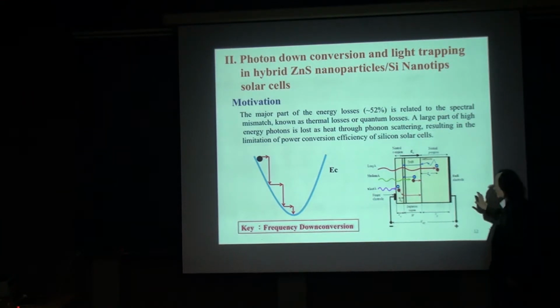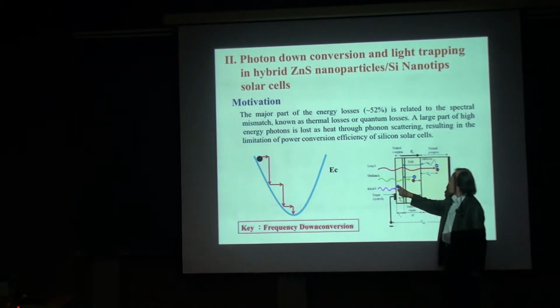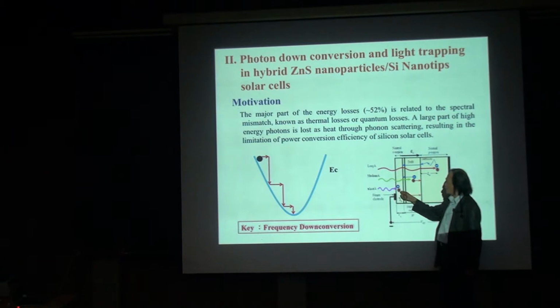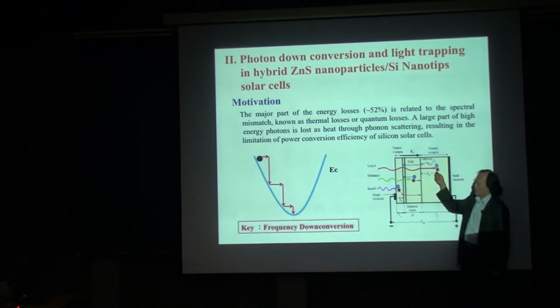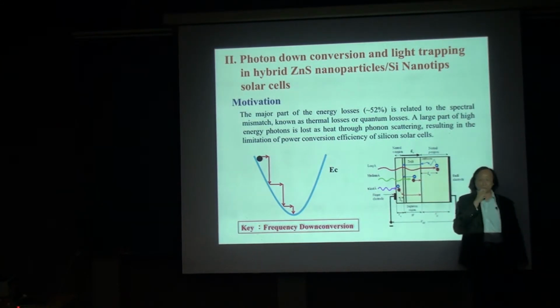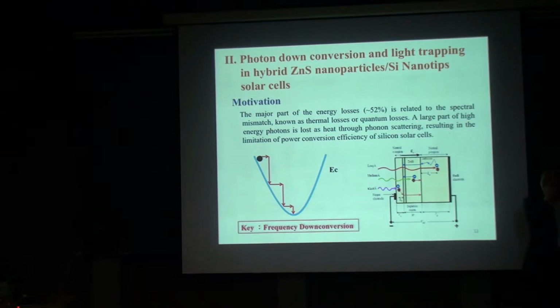So understanding this mechanism, the problem right now is to overcome the generation of electron-hole pairs near the surface. How do we do it? If we can design a material system which can absorb the UV light and emit visible light, therefore we can shift the generation of electron-hole pairs from near the surface to inside the bulk. Therefore, we can enhance the solar cell efficiency. So that's the underlying principle we think about.